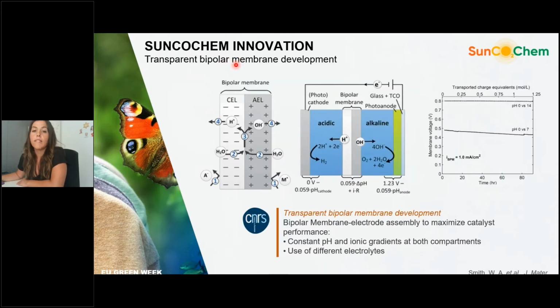Concerning the ionic transport, as I said, we need a very efficient ionic transport. Here we can take a lot of inspiration from PEC devices for water splitting, where it's necessary to work in 2 different pH conditions. So in SunCoChem, we are developing transparent bipolar membranes that can provide protons to the cathodic part to reduce CO2 and OH minus species to the anodic part to oxidize water, and those species are generated by the dissociation of water at the interface of the membrane.